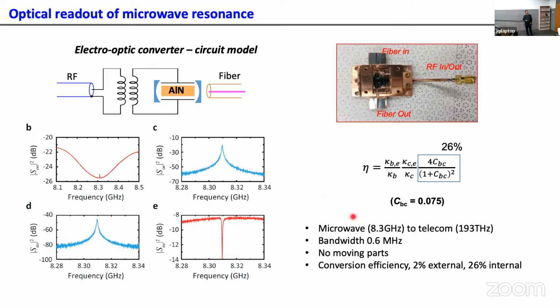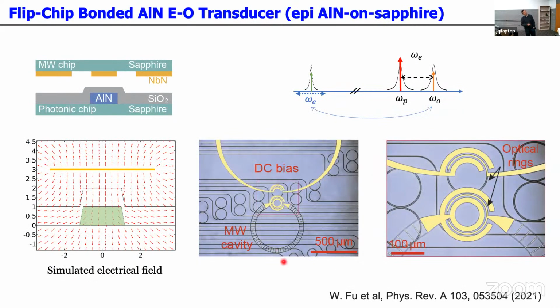In this specific device, we have a cooperativity of about 0.075, and that translates to a conversion efficiency from waveguide to waveguide of about 2%, considering all the loss involved. These devices are made of aluminum nitride without any moving part, originally polycrystalline aluminum nitride. Recently we're making them with single crystal aluminum nitride. We also made lithium niobate. Efficiency is not necessarily getting better, but we see that the noise gets better. This is a single crystal aluminum nitride. The structure is a little bit more complicated, but it's the same principle. You lay down a microwave circuit resonator and an optical resonator and do the phase matching,